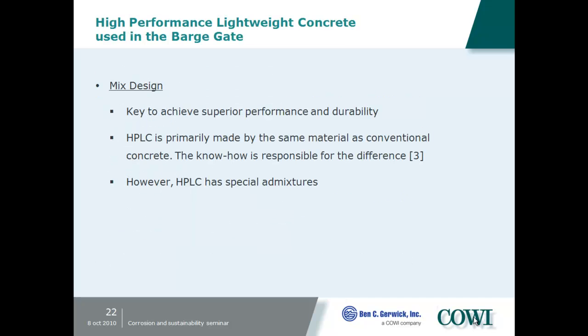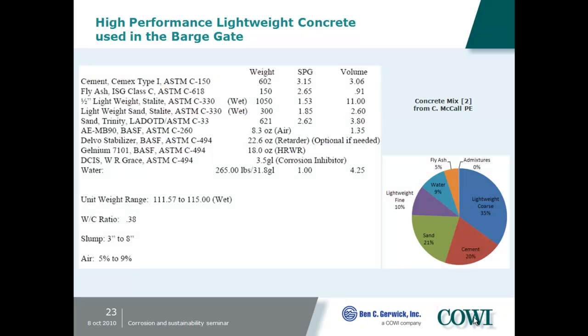So here's the mix design that we used to achieve this type of performance. We had fairly high cement content and fly ash as well. And this is the Stalite. It's very good quality lightweight aggregate. For high strength concrete, you need to have good quality of lightweight aggregate. And Stalite from North Carolina is some of the best in the country. We also had local sand and air entrainment, high-range water reducers.